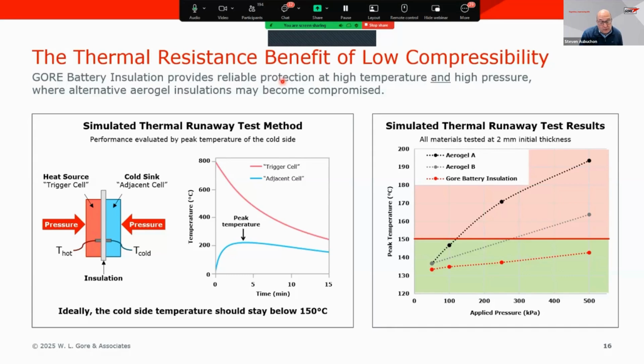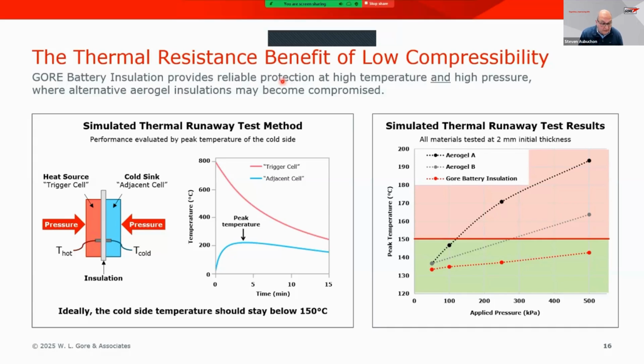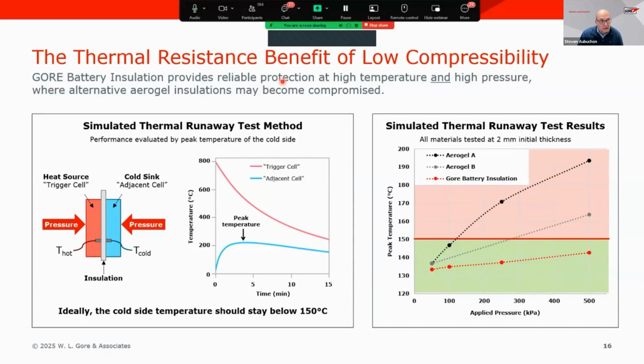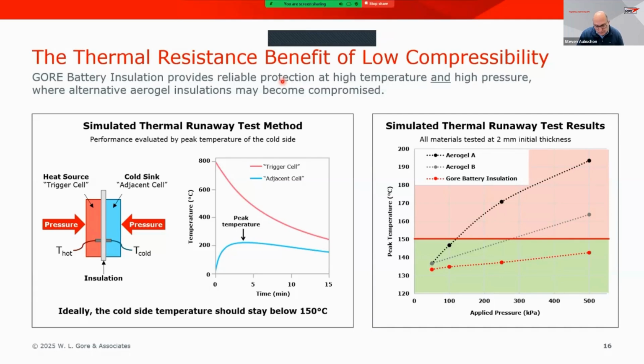And it's also a little bit more problematic from a particulation perspective. So I'd say the relevant alternative insulation material is often delivered in the form of some sort of scrim, and the aerogel is adhered to that, and then it's encapsulated as well. And so whereas aerogels are very low density, the alternative materials that need to be deployed typically raise the density of those solutions into the same typical range as Gore battery insulation in that 0.3 to 0.5 gram per cc range. So we're at a comparable density, but remember, weight is not just density, it's how much you're deploying.